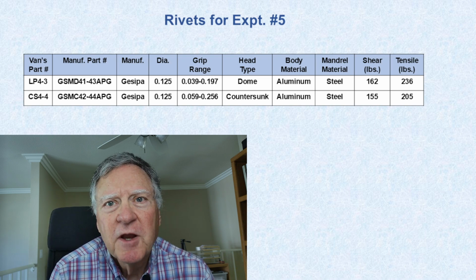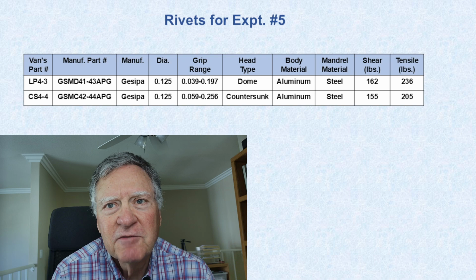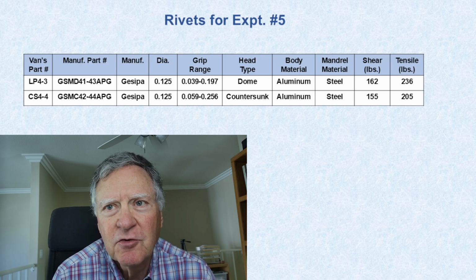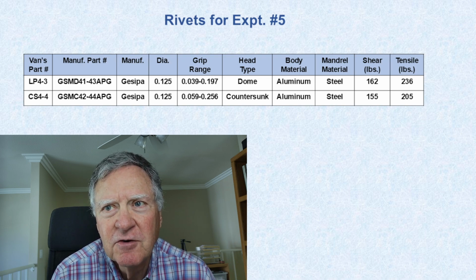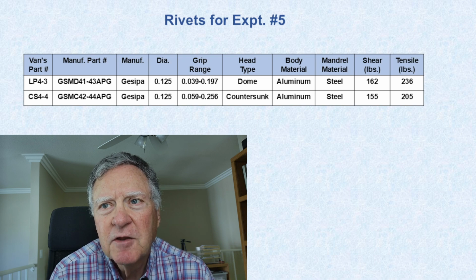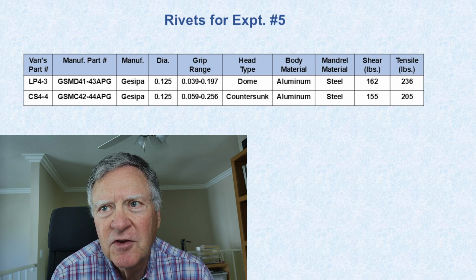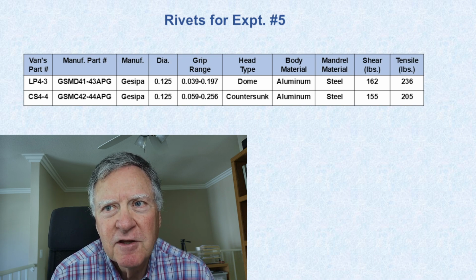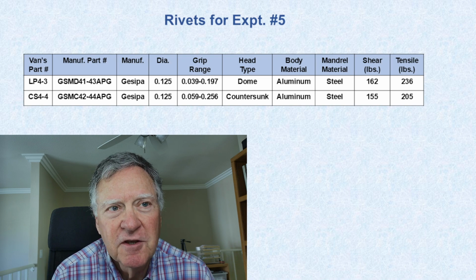So the LP 4-3 is a dome head rivet. The body material is aluminum, and the mandrel is steel. And according to the manufacturer, the shear strength is 162 and the tensile strength is 236 pounds. Now, that I'm sure is for thick aluminum, basically the optimum case. And I'm going to be measuring the tensile strength for thin aluminum.